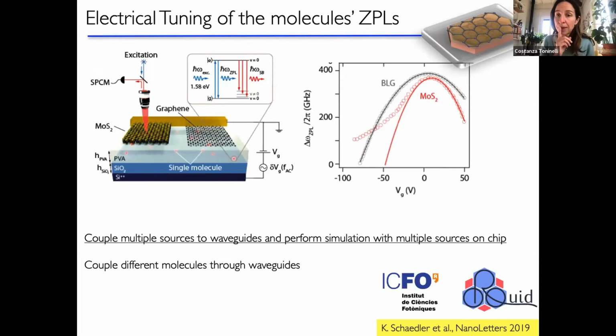So actually, we're talking about a molecule that's centrosymmetric, which means that it doesn't have any permanent dipole moment, and hence this voltage-induced shift is to be ascribed to a second-order Stark shift, which means it's not huge. That also means that the transition frequency of the molecule is stable, because otherwise it would suffer a lot from the surrounding noisy charge environment.